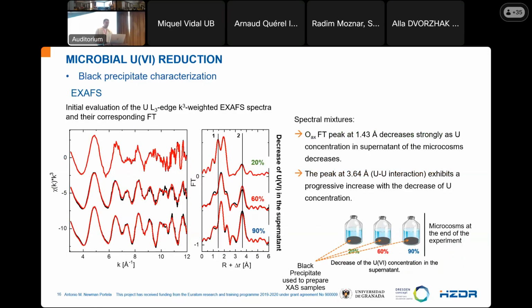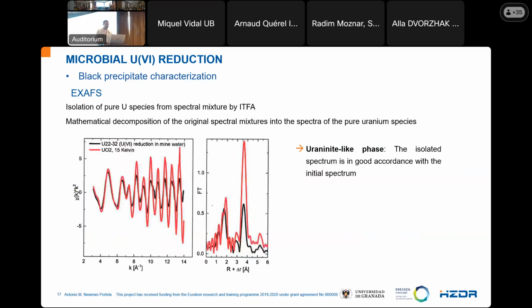Here you will observe the initial evaluation of the uranium L3-edge k3-weighted EXAFS spectra and the corresponding Fourier transform. We observe a decrease in the peak at 1.43 angstrom, related to uranium-6, and an increase in the peak at 3.64 angstrom, related to uranium-4. When we analyze this mixture spectra, we were able to isolate by ITFA a uraninite-like phase. So that means that we prove the uraninite formation at the end of the experiment. Our sample is the black line, and the red line corresponds to the reference.